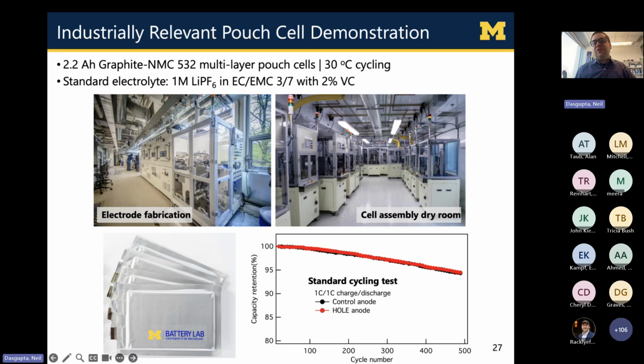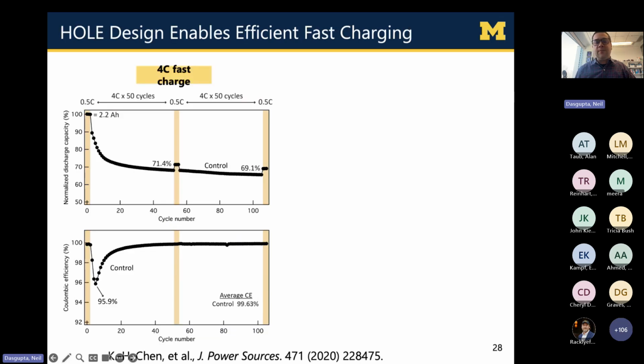And what we see is that if we just do a standard 1C charge discharge profile, the control anode and hole electrode give essentially the same behavior. But we see dramatic differences when we start moving to these fast charging conditions. If you take that unpatterned electrode and do 4C fast charging, meaning a 15-minute recharging time, you see that after 100 cycles, we've already lost 30% of the capacity of the battery. That would be totally unacceptable to an EV customer.